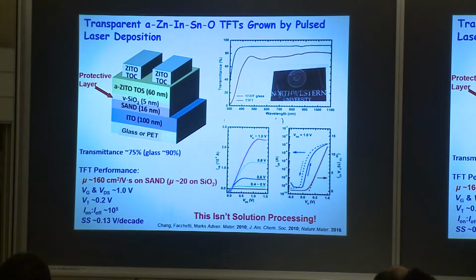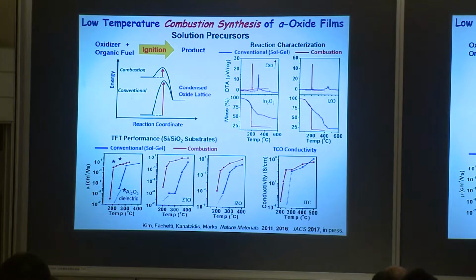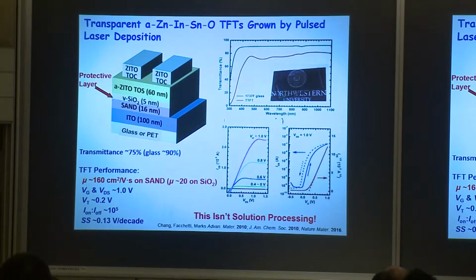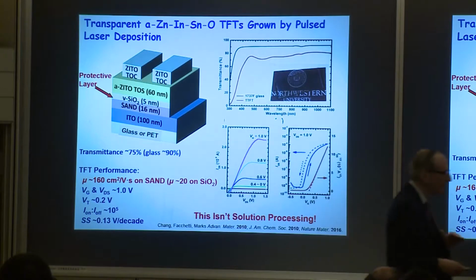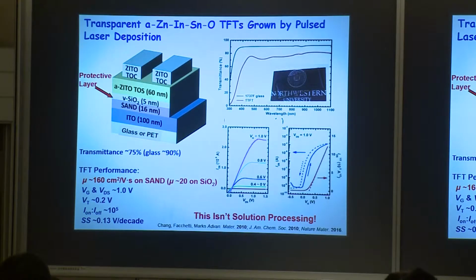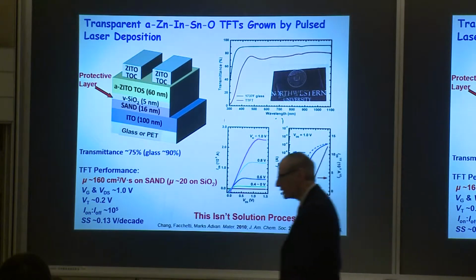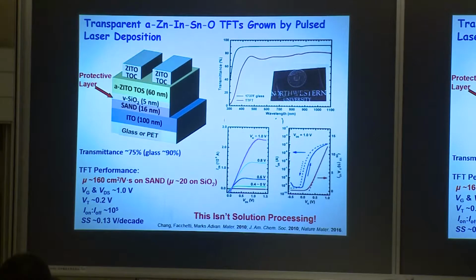And let's take it one step further. The problem, you might say, well, okay, Bob, your pulsed laser deposition is great, but this isn't solution processing at all. So how does one solution process something like this? Your first thought is there's a technology that probably some of you know called sol-gel processing, where you hydrolyze an organic precursor. You take this very thick, I shouldn't use the word goo, let's say sol, and spread it, and then you heat it to 400, 500, 600 degrees C to densify the lattice. That's good, but what plastic are you going to use for heating it? You can't do that.